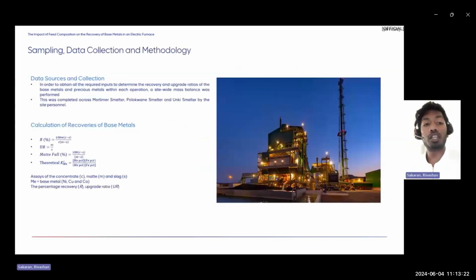In terms of how the data was collected, ultimately the metal accounting data, which measures the inputs and the outputs of the smelters, was used, and this is done on a monthly basis. Ultimately, how metal accounting samples work is that a site-wide mass balance was performed, and this was used to get the concentration data of all the concentrate entering the furnace, the concentration data of the slag that's removed from the furnaces, and the concentration of the matte that's leaving. This is done on a monthly basis to prevent any variances in the